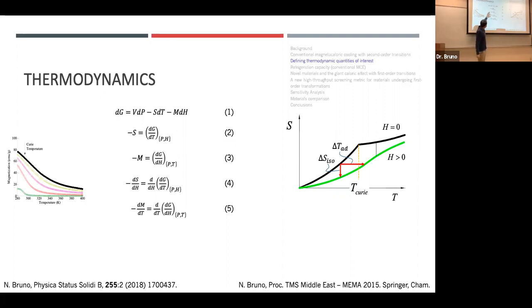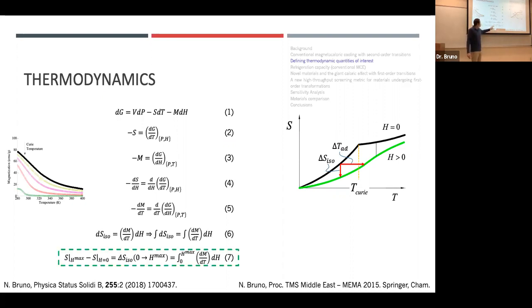So we have dS/dH equals dM/dT. Maxwell relationship. We can separate the equation and integrate. And what this says is the isothermal entropy change equals the integral of dM/dT. That's our thermomagnetic response. And we integrate from 0 to some applied magnetic field. So if you were going to find the isothermal entropy change of this material that I show with the graph on the left side here, we would need to find the derivative of this curve, the slope of the curve, and we multiply by some field level.